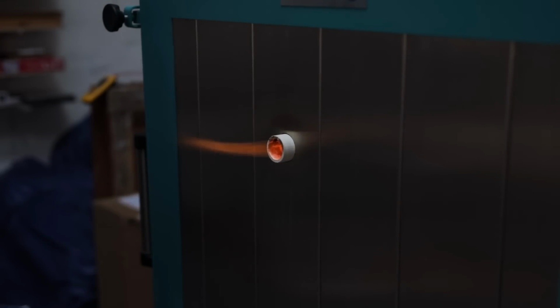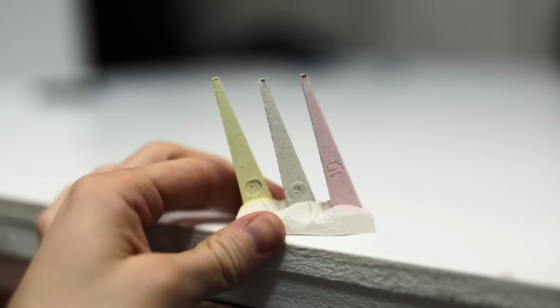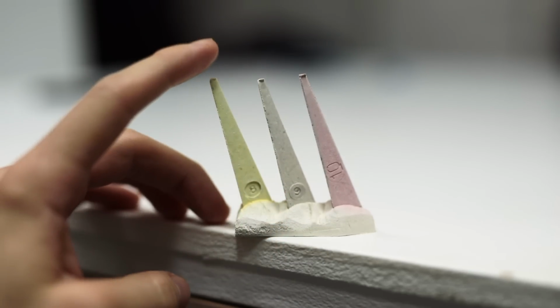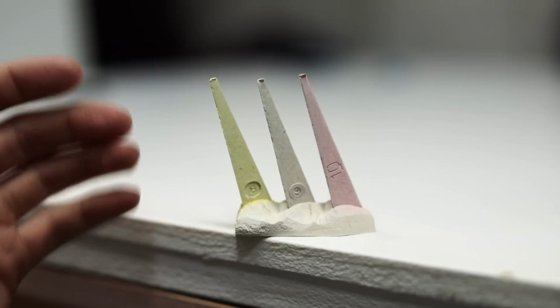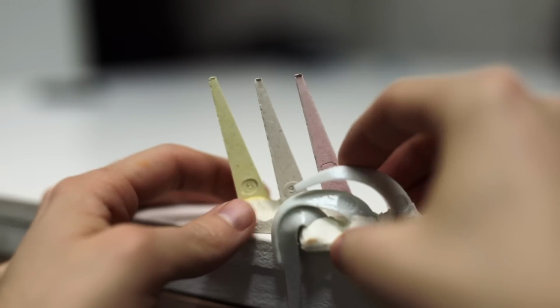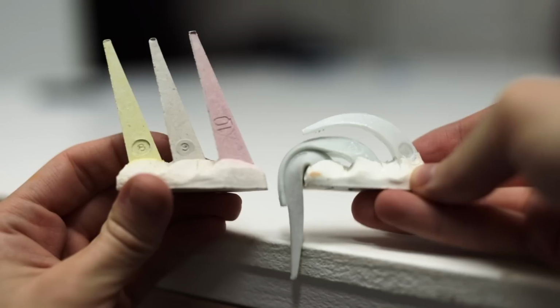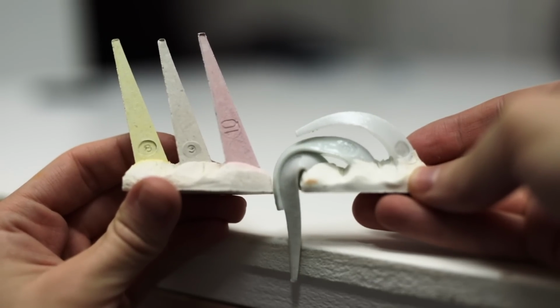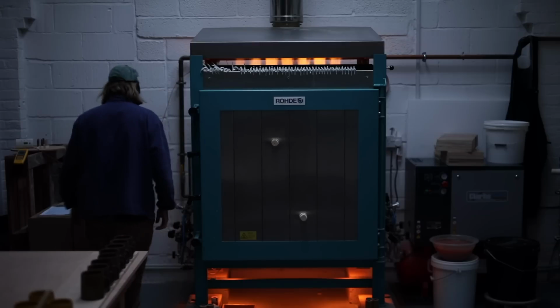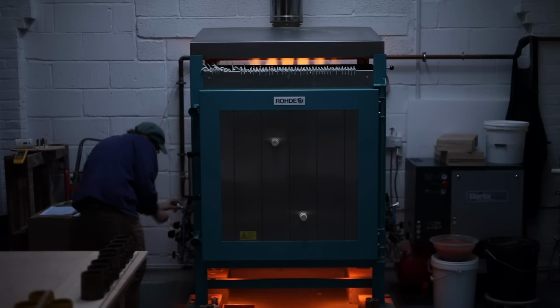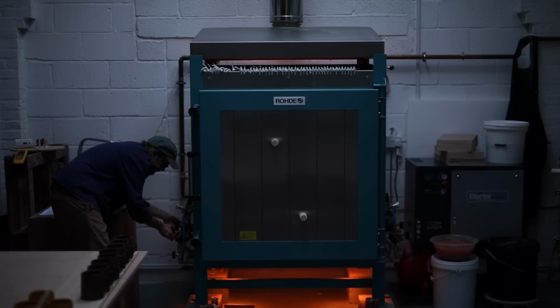I measure whether the heat is going up and down by following the digital pyrometer, but there's also something else I'm watching which I can only see through these spy holes, and that's observing pyrometric cones I've packed alongside my pots inside the kiln, which you can just about see here, bent over. This is what they look like before they're fired, and as the temperature increases past certain ranges, these very slowly melt and bend over, measuring heat work, which is heat over time, and here's what they look like afterwards. And when they're all roughly in this position, I know it's time to conclude the firing, which is usually at about 1300 degrees Celsius, and after about 8.5 hours, the noisy kiln can finally be switched off.